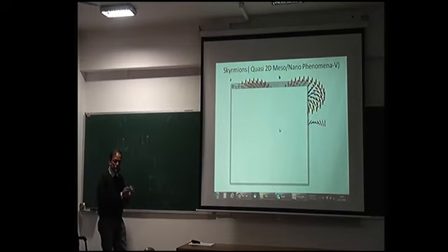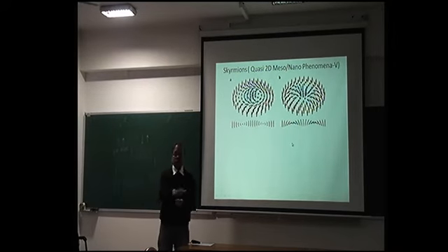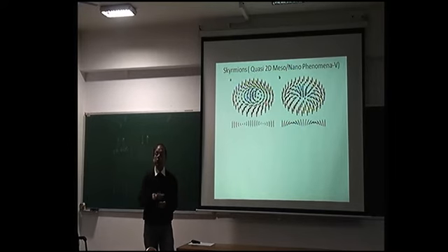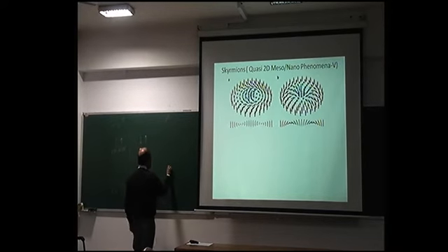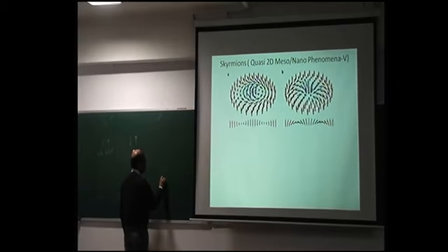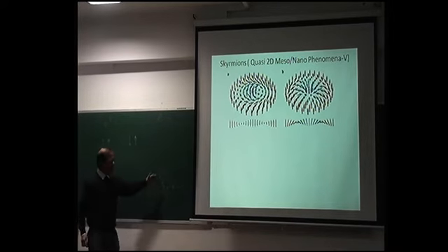Now, if you switch on this kind of interaction between 2 spins, you won't get ferromagnetism, you won't get antiferromagnetism, you will get this kind of topological spin texture in 2 dimensions. And it has been observed in certain materials called MnSi, then iron germanium, and the most studied one is Fe x Co 1 minus x silicide. There are also heavy metal thin films.